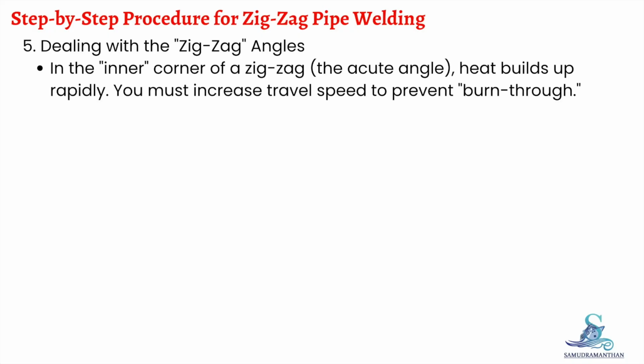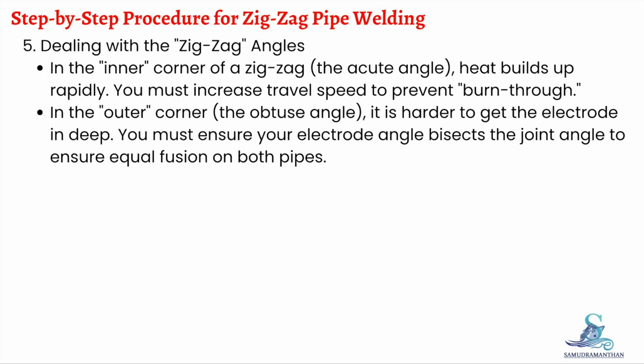In the inner corner of a zigzag, the acute angle, heat builds up rapidly. You must increase travel speed to prevent burn-through. In the outer corner, the obtuse angle, it is harder to get the electrode in deep. You must ensure your electrode angle bisects the joint angle to ensure equal fusion on both pipes.